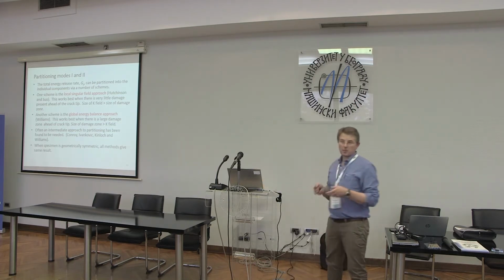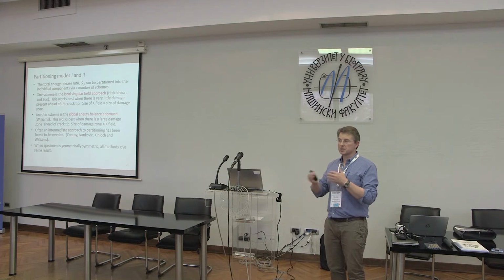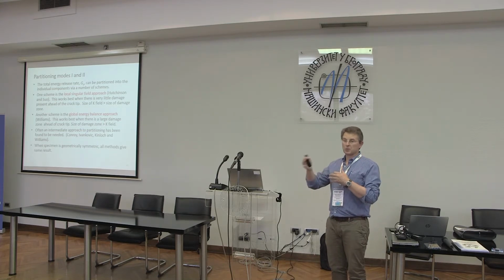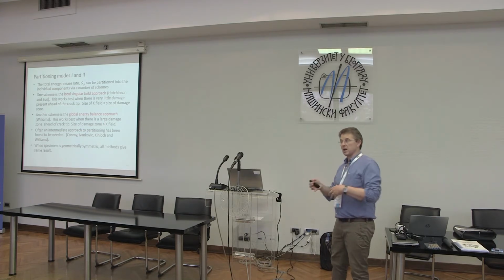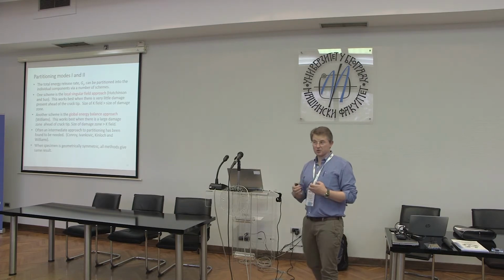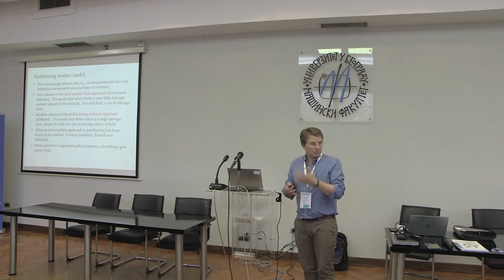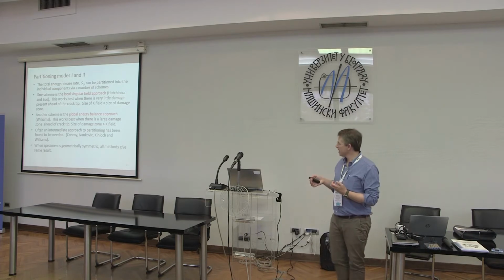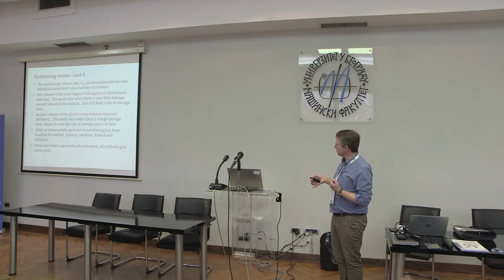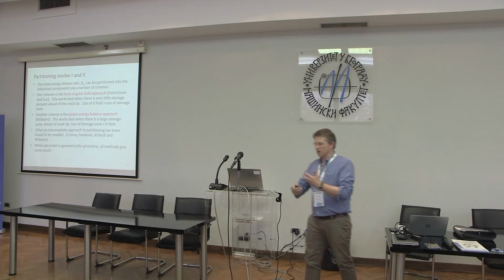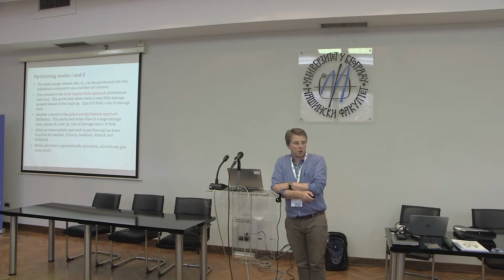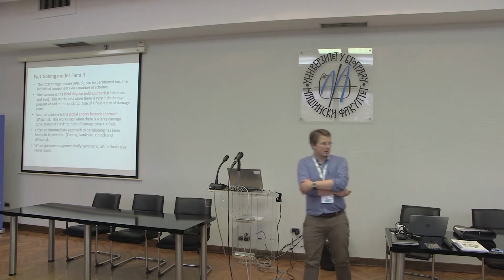Now, if you try and apply that partitioning scheme to a system where the damage zone is large, and the damage zone is much larger than the K-controlled zone, you get ridiculous values. It doesn't work. So if you've got a scheme where that is working, then, where you have the large damage zone, you're much better off with a global analysis. Okay? So big damage zone, global analysis, small damage zone, local singular field approach is best.